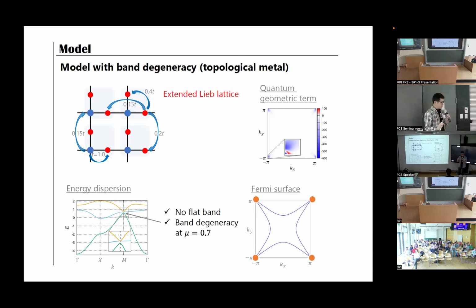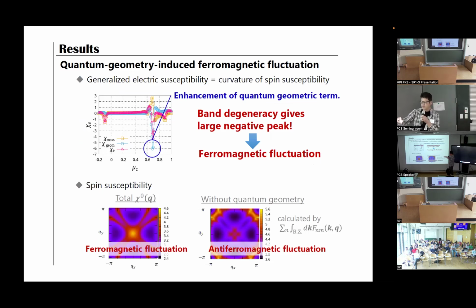So consistent with our expectations, the quantum geometric correction to the curvature of spin susceptibility is negative in this case. It mainly comes from the momentum space around the